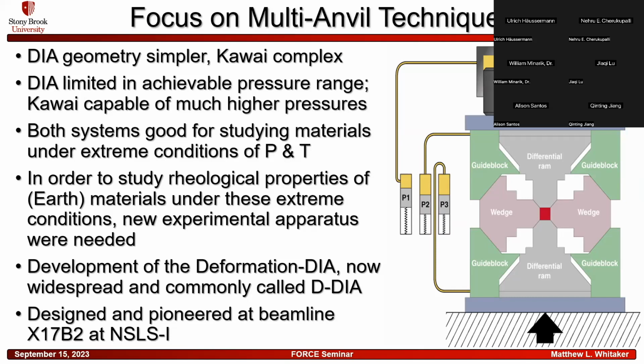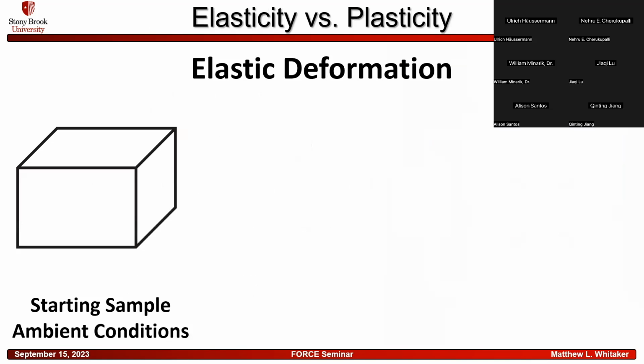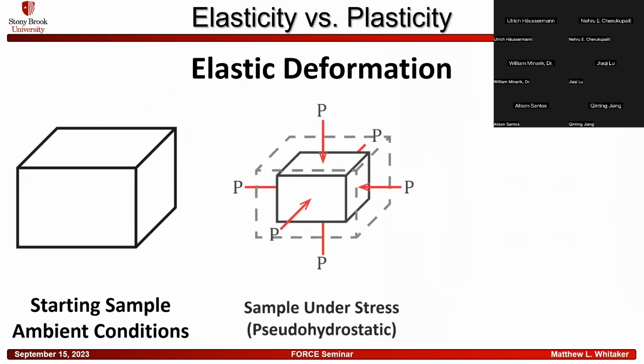So the diagram at the right shows that you can compress the entire thing together as you push the top and bottom together. The wedges come in from the sides on the 45-degree guide block. So you produce a pseudo-hydrostatic pressure on the sample. But then you can drive the differential rams, top and bottom, separately, and you can use that to deform the sample as well. So you can make it shorter in one direction. And those experiments help you understand the strength and the rheological properties of the material. So why do we care about that? It's a difference between elasticity and plasticity. In elastic deformation, you have a sample sitting at ambient conditions, and then you add pressure to it.